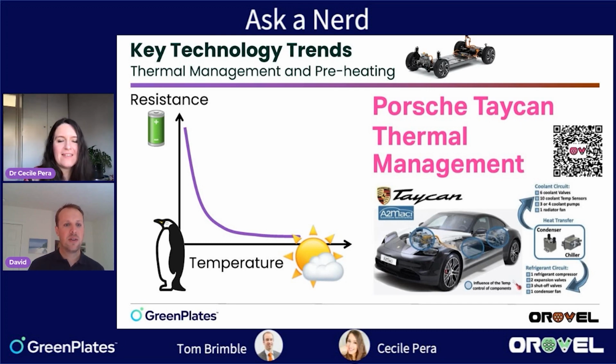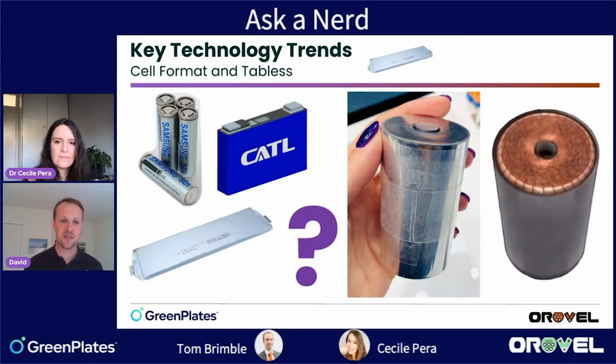Yeah, and we're talking, typically you'll operate a battery at maybe 20 to 30 degrees, like during normal driving. So if it gets above 30, you'll start cooling it quite aggressively. And then once you get down to 20, you'll really back that off because you start to lose performance if it goes too much colder. Batteries are great in that they do generate a little bit of self heat to bring them up to those operating temperatures. During fast charging, I don't think you'd target much above 40 to 45 degrees. We're not talking really high temperatures.